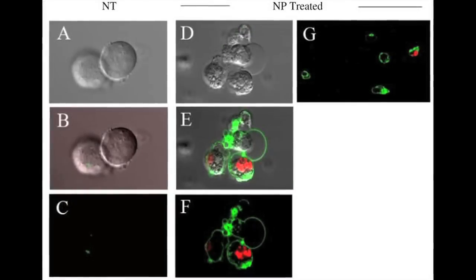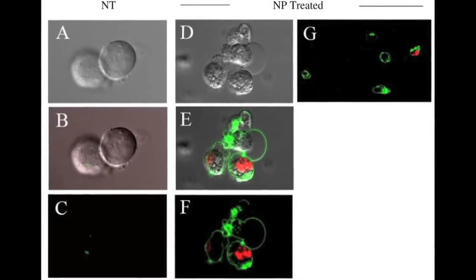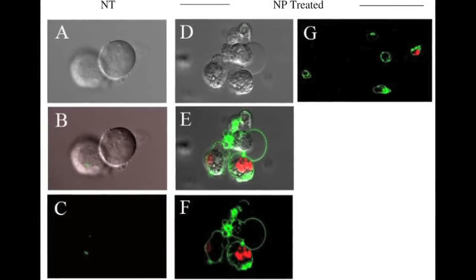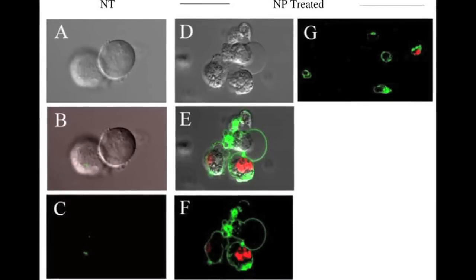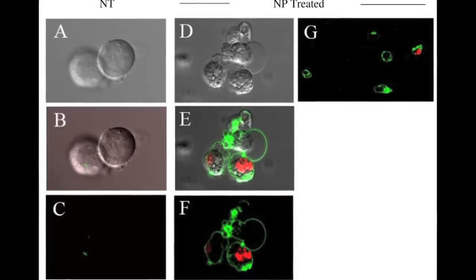Our zinc oxide nanoparticles were about 35-fold more efficient in killing the cancer cells that were tested compared to killing the normal healthy cells.